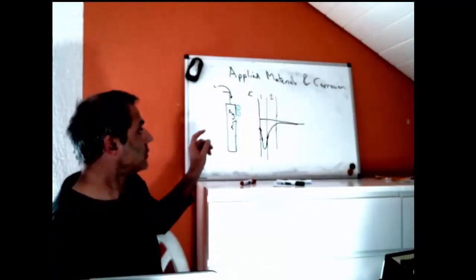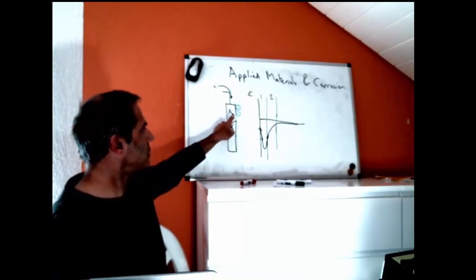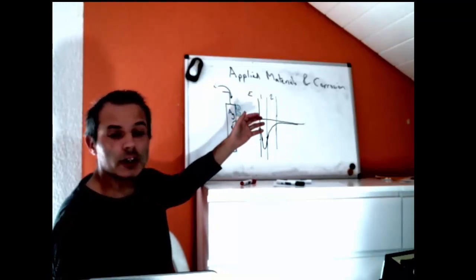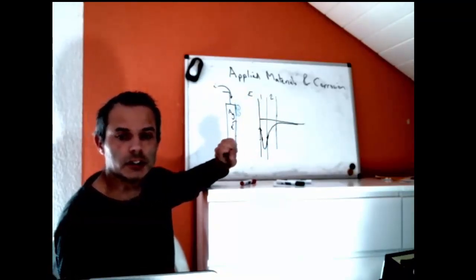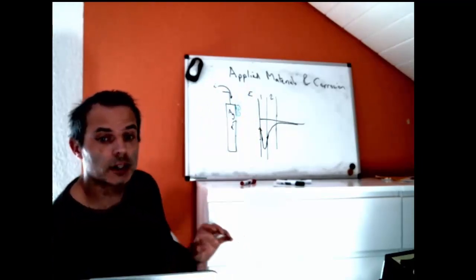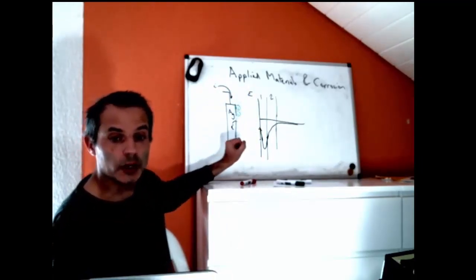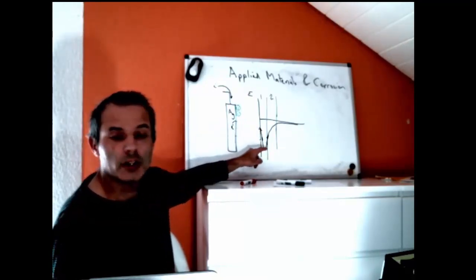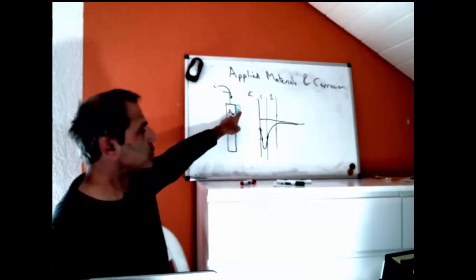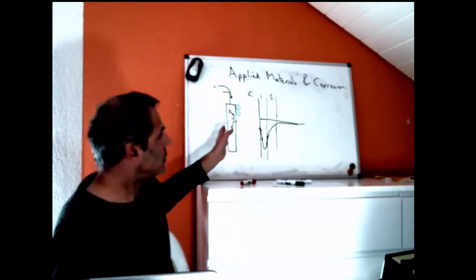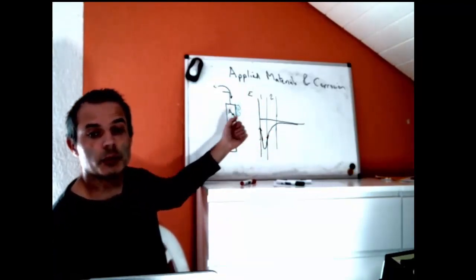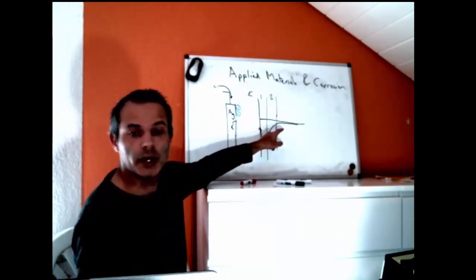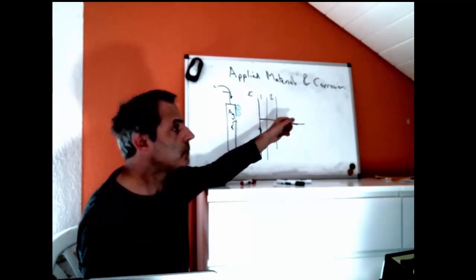So looking in closer to the electrode, we can see in some cases, so I've changed my electrode to silver now, and at the surface of silver you would imagine that the chloride ions would love to stick to it because silver chloride is a very stable solid. If we have a layer of chloride ions at the surface of the silver bound to it, we would have a lower voltage, more negative voltage, than we're actually thinking that we've put on there, because we've got lots of negative charge. And then outside that, obviously, because it's very negative, there will be more sodium ions and less chloride ions. And so the voltage will come back to close to zero.